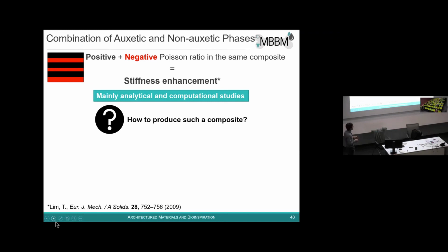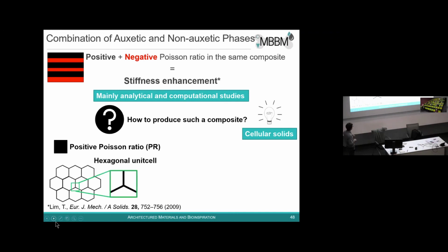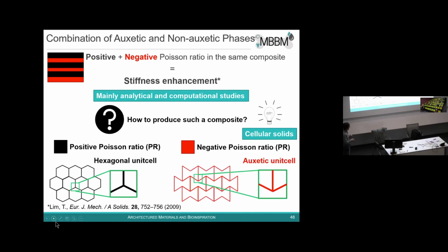And then we said, okay, maybe we could use cellular solid principles, design lattices that show a combination of reentrant auxetic inclusion and non-auxetic inclusion, and see which type of behavior we can have. So we combine so-called hexagonal lattices, which show classical positive Poisson ratio behavior, with reentrant lattices, which are quite simple lattices that show this auxetic behavior. And then we said, okay, what happens when we combine those two?